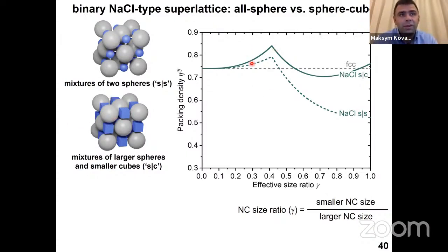And so here you see that, for instance, when you mix two spheres, they will have high packing density only in a specific size range. And only then you will have this lattice more stable than the phase separation into single component lattices. So basically you compete against phase separation, and you will win this competition only if your resulting lattice is denser or similarly dense. So with cubes, it's actually even easier because the cube of the same diameter as the sphere is larger. And so you can get higher packing densities when you switch from a sphere to a cube.